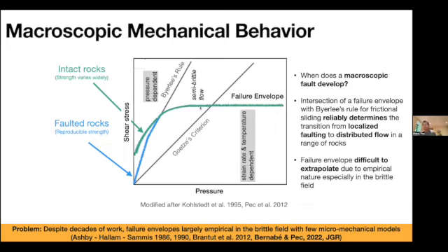And after that, we're entering this semi-brittle flow field until we reach this so-called intersection, which is sometimes called the brittle plastic transition, where we intersect this failure envelope with the Goetze's criterion. The Goetze's criterion is just an experimentalist rule of thumb, which basically says that if the differential stress is lower than the confining pressure, then you are likely deforming the rocks by some crystal plastic processes.